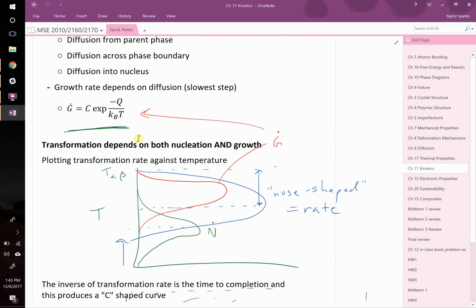Nucleation occurs at one maximum value because it's competing with the number of critical nuclei that takes off, and diffusion, whereas this thing just competes with diffusion up there, right? So those two things convoluted together give you your total rate of transformation, okay? Again, maximum rate corresponds to a minimum time, so that's why you get this nose in the TTT diagram.